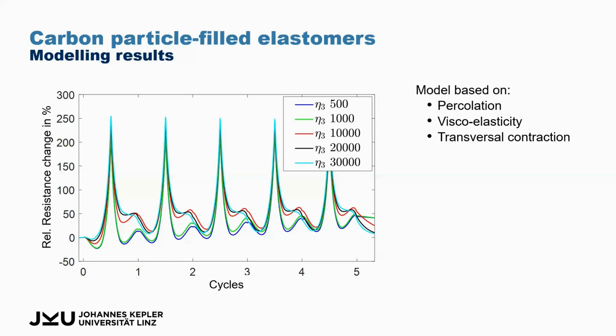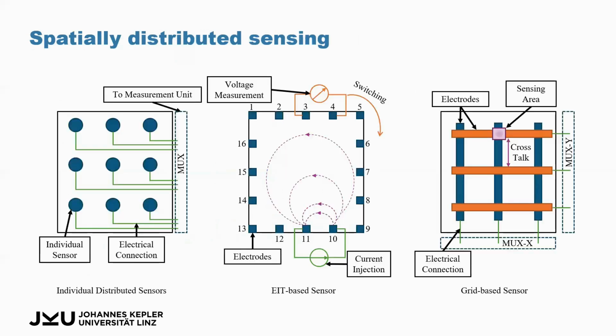And this model is based on the percolation, the viscoelasticity, and the transversal contraction, because we assume that this phenomenon is based on different time constants of longitudinal and transversal contraction. And besides the long vision of having large area, very stretchable, very compliant sensors, having distributed sensing allows us also to better characterize these phenomena. Now, there are different approaches to this. You can have distributed sensors, EIT, so electrical impedance tomography, or grid-based sensors. And I'll just show you a first approach of what we did with grid-based and electrical impedance tomography sensors based on these stretchable carbon black silicone materials.